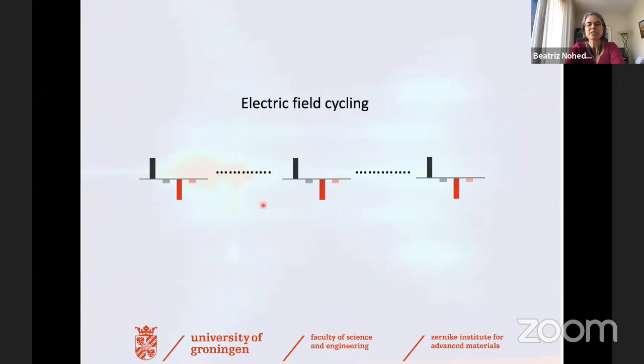So we did some cycling in these tunnel junctions. And I have to say that these tunnel junctions are very robust in the sense that from device to device, all the devices made in a film actually work, and the results are very similar in all the devices. But you can see things happening after electric cycling. And depending on the amount of cycles that we have subjected the tunnel junction to, we are calling different stages A and B and C. Stage A is the original stage that I just explained at the beginning of the cycling of the sample.